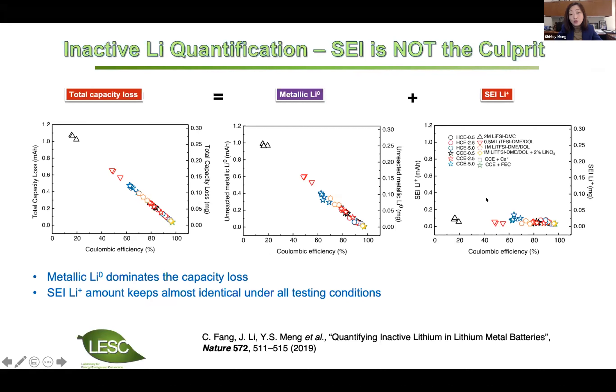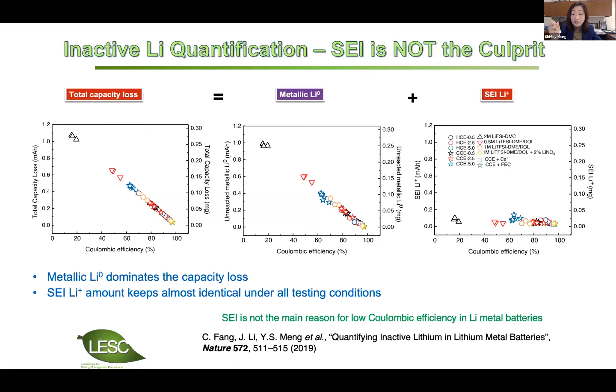This experiment tells us that in low-efficiency electrolytes, metallic dead lithium dominates the capacity loss — it's not the SEI. We measure almost similar SEI amounts across conditions. SEI is still important, but we need to solve the dead/inactive metallic lithium problem first. SEI becomes the main limiting factor only above 99.6% efficiency. Many electrolytes are now reaching 99.6%, but to go to 99.9%, SEI becomes the 'secret sauce.'